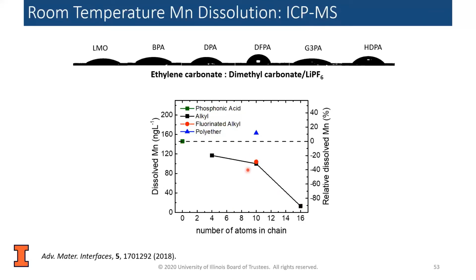As you can see, the fluorinated alkyl is about the same as a 10-member alkyl. Polyether had the most, so it proved to be the least effective in terms of preventing the dissolution of the manganese. And so here are some examples of how you can come up with schemes to tailor the amount of wetting to vary the performance of the battery. Maybe you'll want to make them very high performance at the beginning, or have some that have a more extended lifetime.